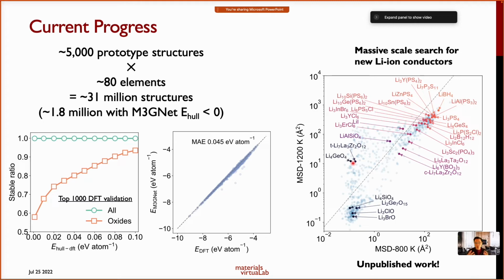Because we have a universal potential, we don't need to just do relaxations, right? We can do MD simulations as well. We can do these MD simulations for a large number of different chemistries. These are all lithium containing materials, and what we can show is that by doing this, we can actually identify good lithium superionic conductors, and the existing ones all actually fall within this regime of this plot, and there are actually a lot more data points out here that we are now exploring.